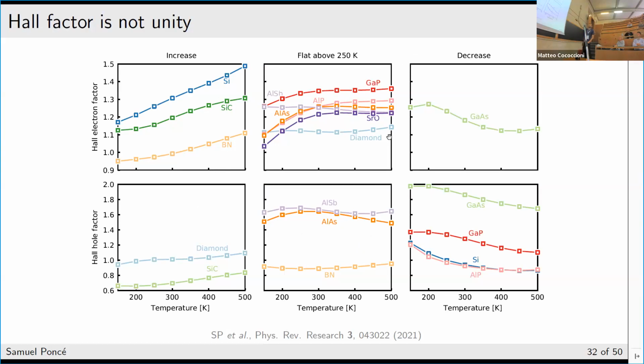I want to mention that the Hall factor is something relatively complicated. It depends on temperature; sometimes it goes up, sometimes it goes down, sometimes it's flat, and also it's not 1. In many textbooks, it's assumed that the Hall factor is basically 1, and so often the drift mobility is taken to be the same as the Hall mobility, but you can see that it's not. So it's very important to compute the Hall factor in order to compare with experiment.